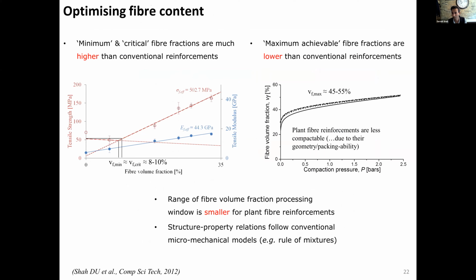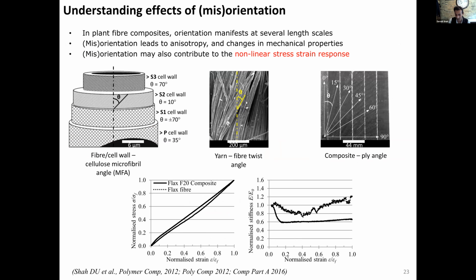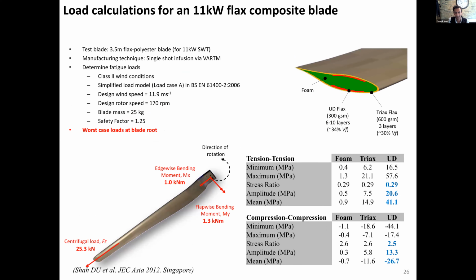One of the other limiting factors about natural fiber composites is you have a critical and maximum fiber volume fraction, which is a narrow window within which you can process. And it's quite hard to produce plant fiber composites in excess of 50% fiber volume fraction, which presents some challenges for the wind turbine application sector. Also, because plant fibers have a nonlinear stress-strain response, you see a stiffness drop in the first few percent strain that is applied, and that needs to be considered during the design of a wind turbine blade.